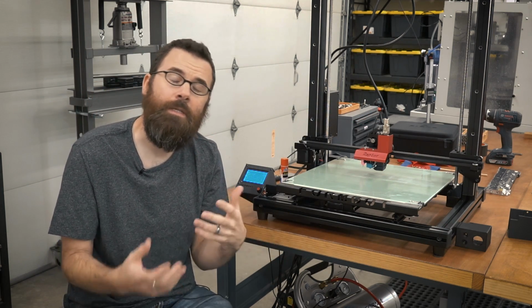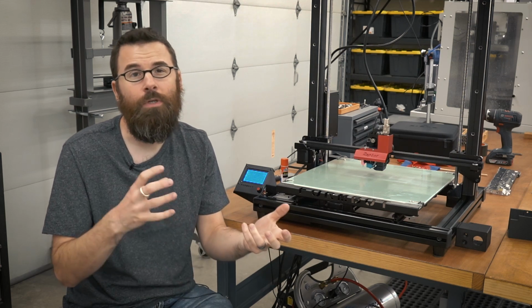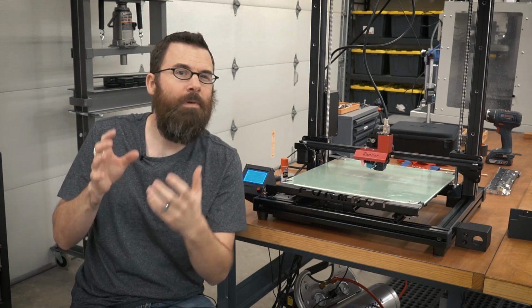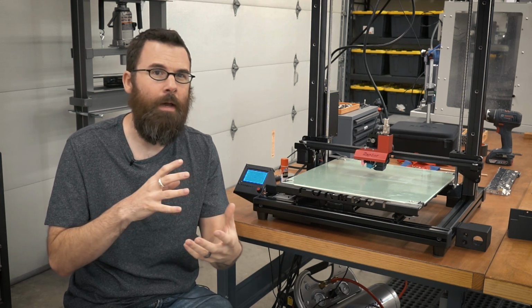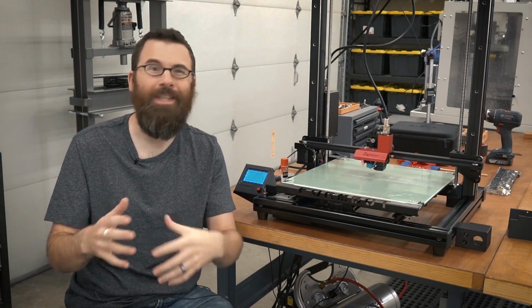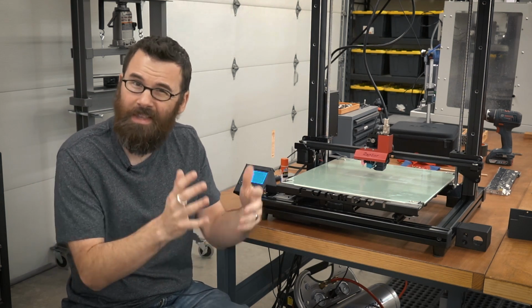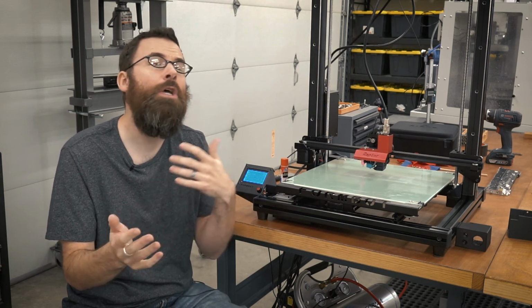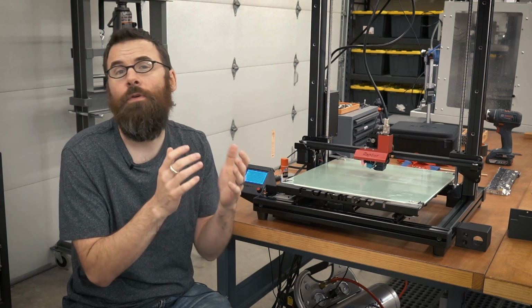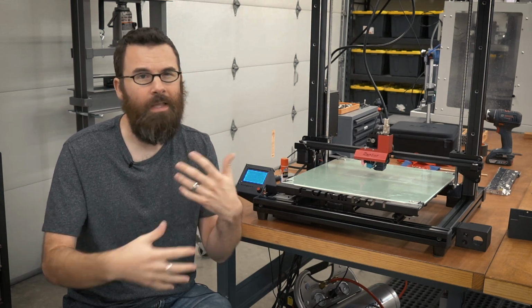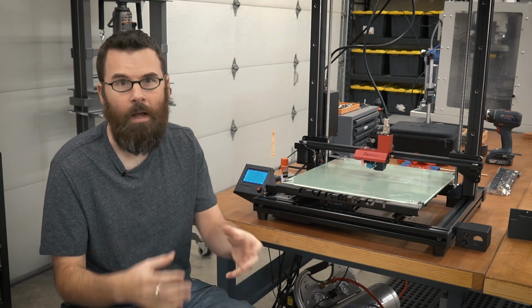Now, Nylon-X, as I said before, is a nylon-based filament with chopped carbon fiber. It is the carbon fiber that is actually doing the abrasive aspect of it. It's actually what's ruining your brass, not the nylon. So if you're using a pure nylon, you shouldn't have to worry about this. But if you're using one with a carbon fiber or some other kind of glass fiber, you're going to have to worry about the nozzle.